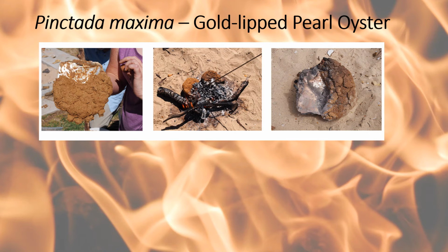So I read about this particular method using fire and thought, okay, this is fascinating. And so we tried it out. So the bit of the pearl oyster that they wanted to retain was covered in mud, and then the whole thing was put into a hot fire. Off the top of my head, it was in there for 10 minutes or so, and then taken out. And you see the outside of the clay is baked.